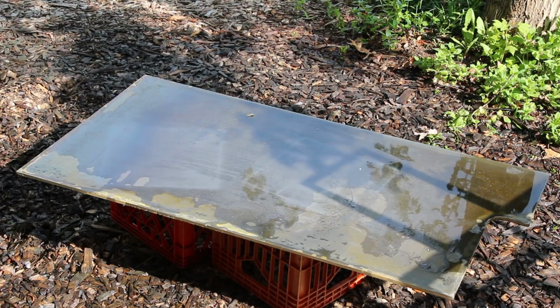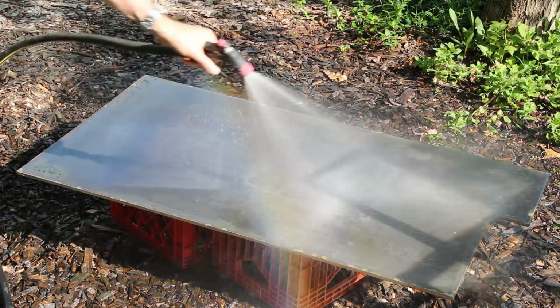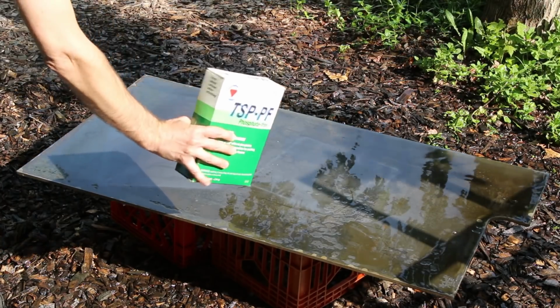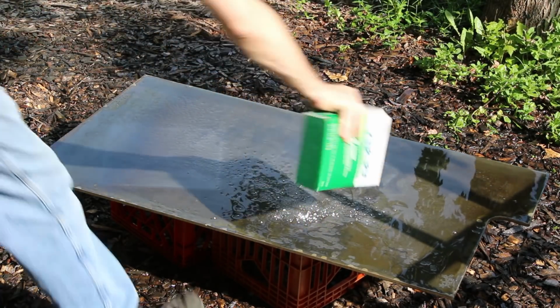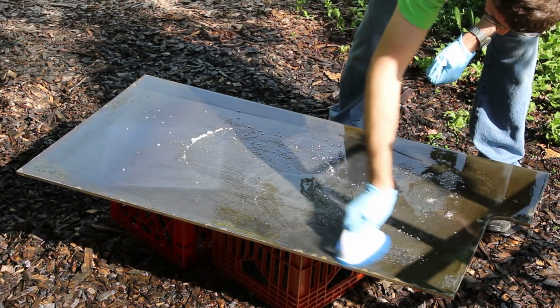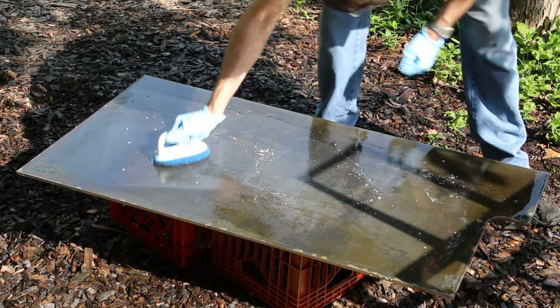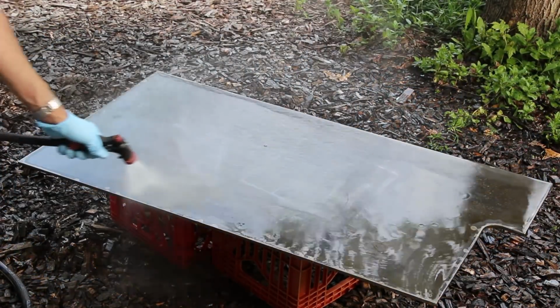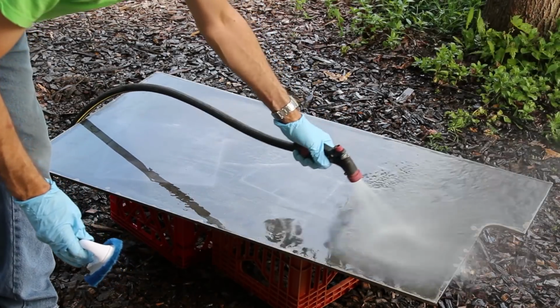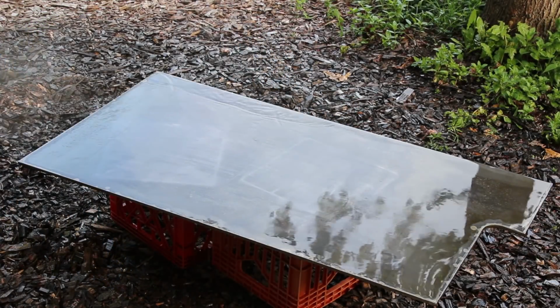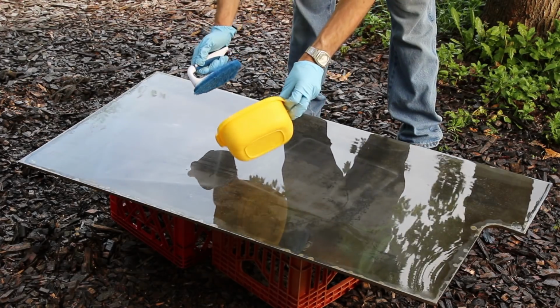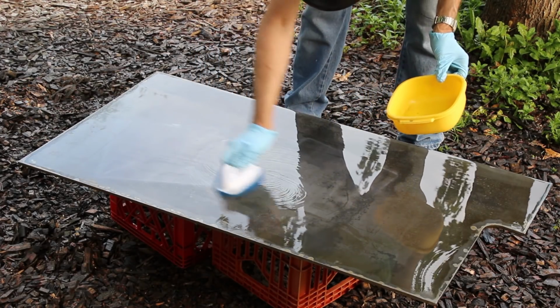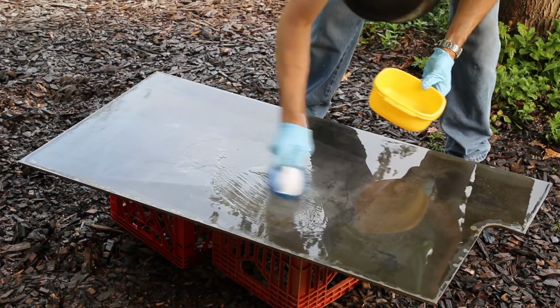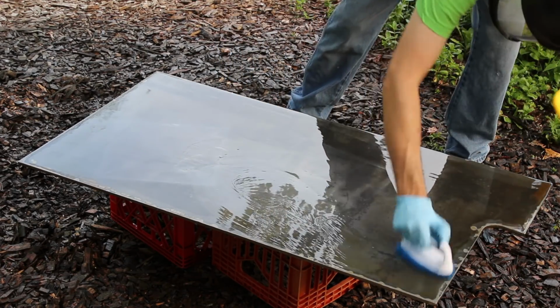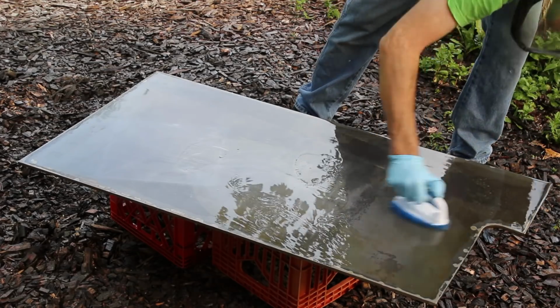The plate is now right side up, so I'm going to do the top now, and the first thing I'm going to do is degrease the surface with a degreaser. I'm using TSP PF, which is like trisodium phosphate without the phosphate. It's a substitute for TSP, but it's a fairly powerful degreaser. And when I tried that on the other side, I found the acid worked 10 times better. So I'll go ahead and do the degreasing, and then I'll apply the acid with it still wet. I'm going to apply it full strength to the wet surface, so it'll get diluted as I'm applying it to maybe 50% strength.